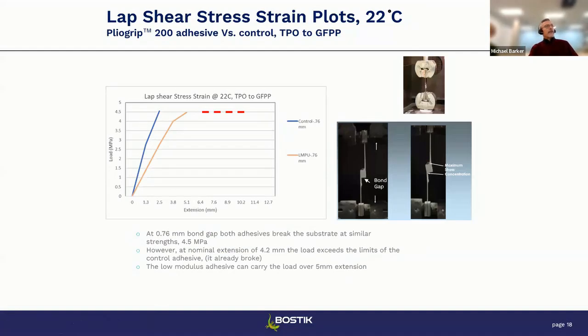So what we did is we put together a series of lap shear, same substrates, always working with the TPO bonded to glass-filled polypropylene. And in this case, we're using a 0.76 millimeter bond gap, and that's about 30 thousandths of an inch. And in this graph, you can see that there are two lines. The first is the control, or the high modulus adhesive. The second is the low modulus adhesive. And a couple of things can be taken away from this graph. The first, the high modulus adhesive and the low modulus adhesive failed at roughly the same strength. Well, that's pretty much what we saw on the previous two slides.